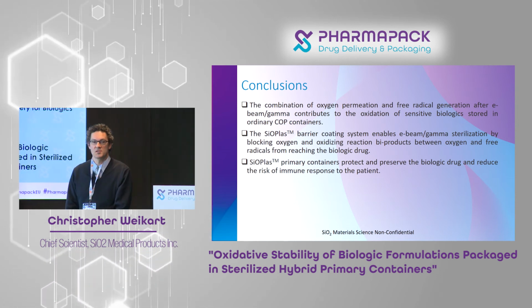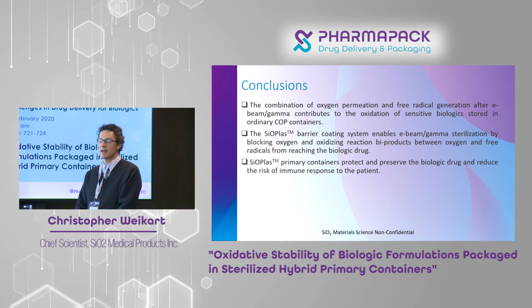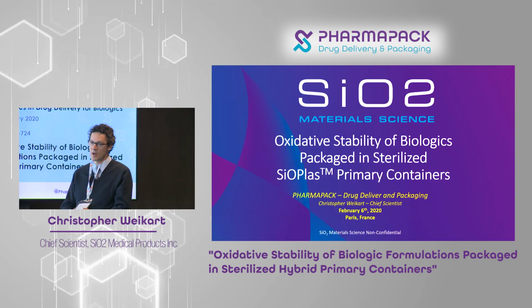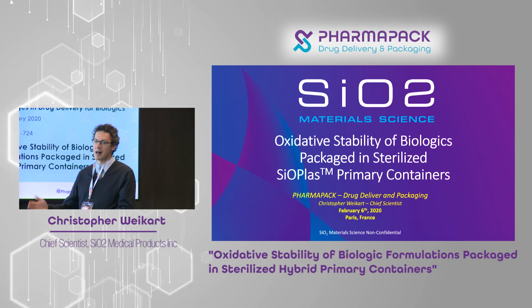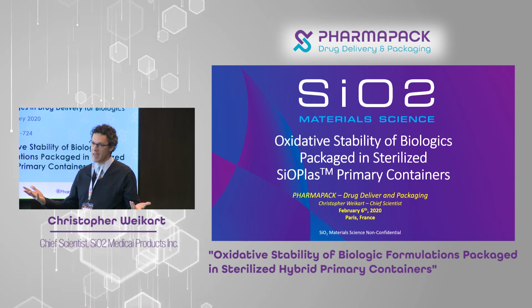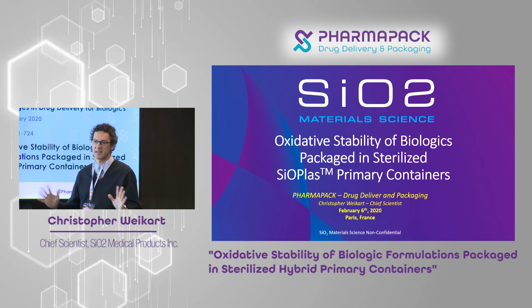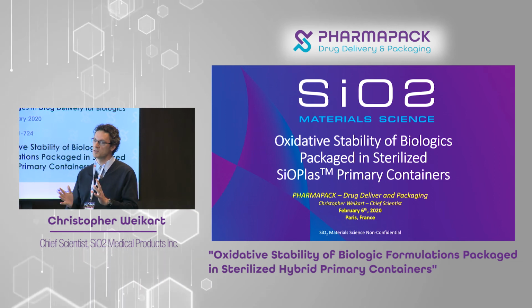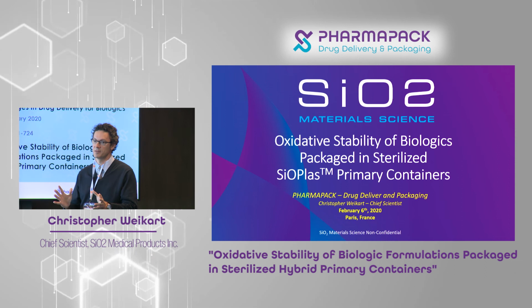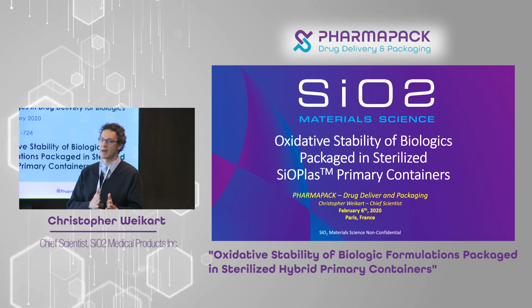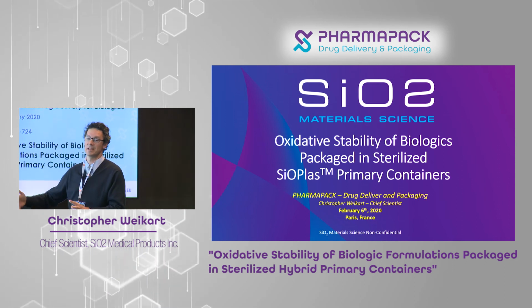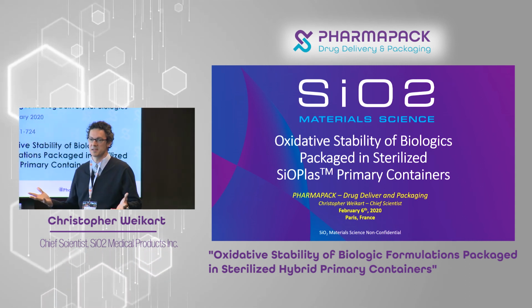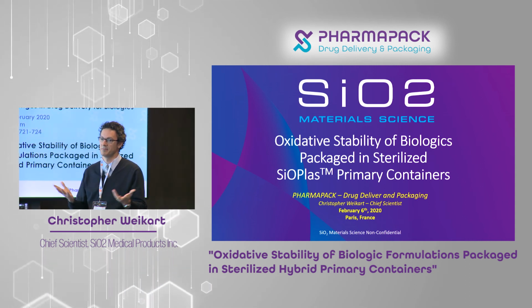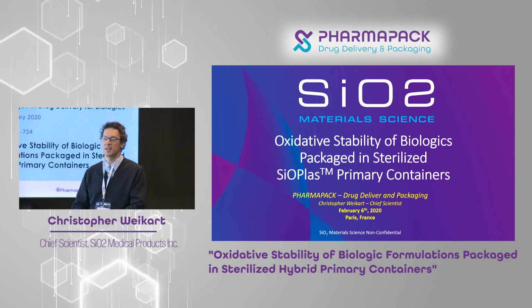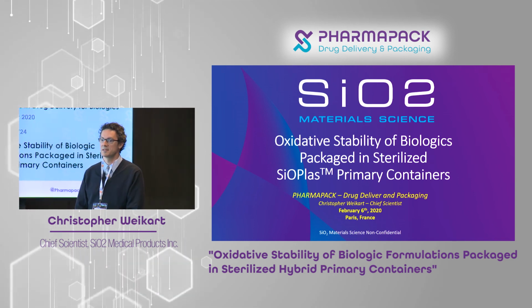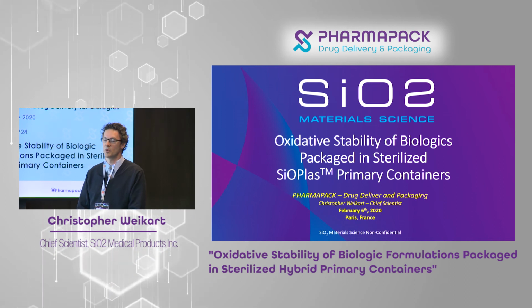Yeah, so certainly the polymer would be affected by that, but it depends on dose. So as you go higher in dose, you'll see discoloration of the polymer, not the coating. I mean, it's again half a micron in total thickness, so that's not going to affect anything. But depending on dose, it's completely reversible for the polymer. You'll see some discoloration, and then it goes right back to clear again. If you go too high a dose, it can be irreversible. But we basically sterilize at a very low dose, and it's perfectly fine. So typically in the range of about 15 to 20 kilograys is typical, and you won't see any color change.